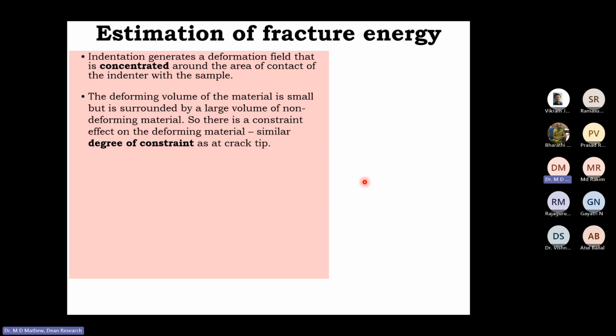The deforming volume of the material is small, but it is surrounded by a large volume of non-deforming material. As the indenter penetrates, the material immediately under the indenter undergoes deformation, elastic and plastic. But then it is constrained by a larger volume of material which is not undergoing deformation. So a degree of constraint is being exercised on the deforming material by the surrounding material. This constraint is considered to be similar to the degree of constraint that exists at the crack tip.